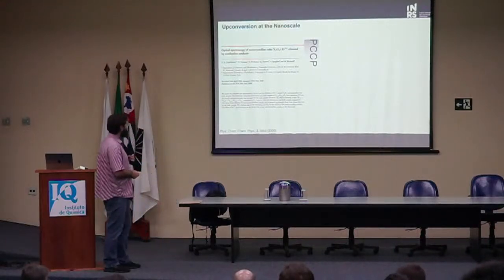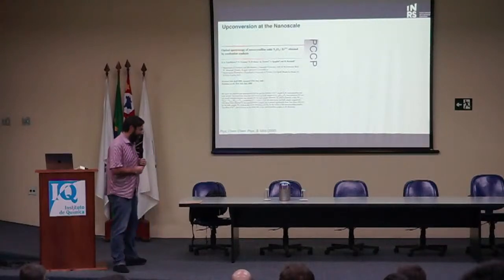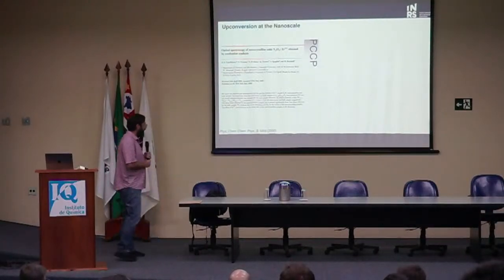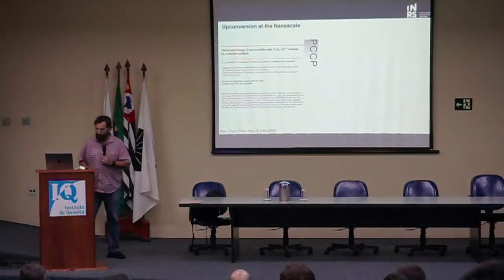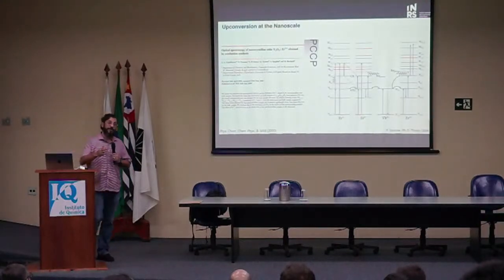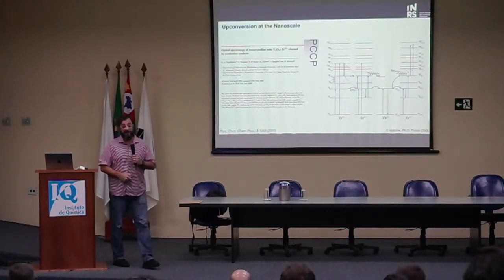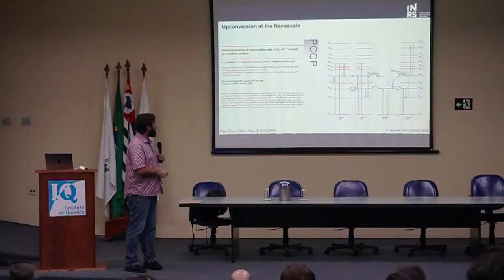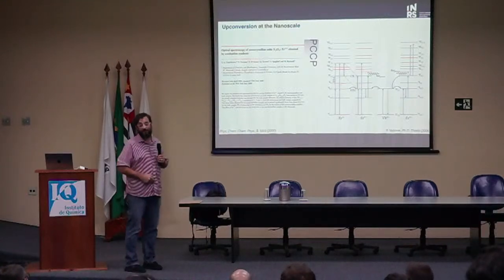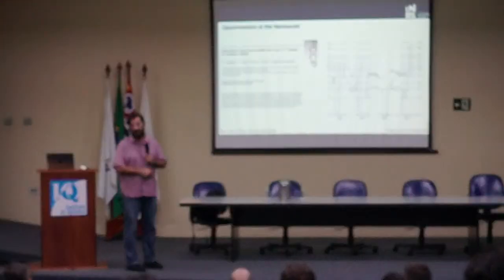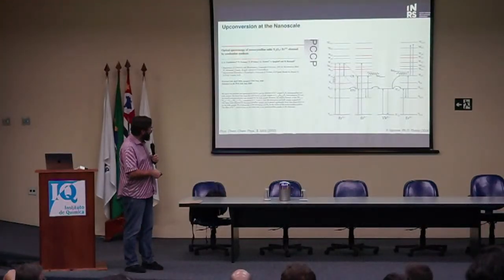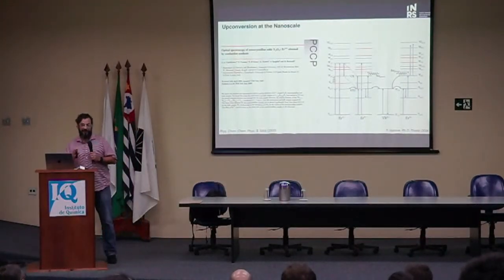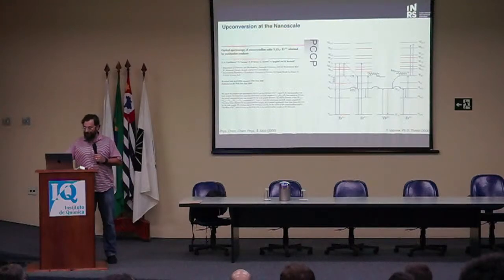So my adventure in this field started 23 years ago. Actually, this paper was published in 2000, but it was a few years before it started. So I would say about 25 years ago. And here, this is where we first showed upconversion at the nanoscale. I could pretty much sum up 6 years of my PhD work here. I didn't even need to write a thesis. I could have just shown this and explained this, and that would have been my defense. So I studied all the mechanisms that led to upconversion at the nanoscale. Spent 6 years in the dark in a laser lab with no windows. So to all you students in the room, don't give up. It gets better, I promise.